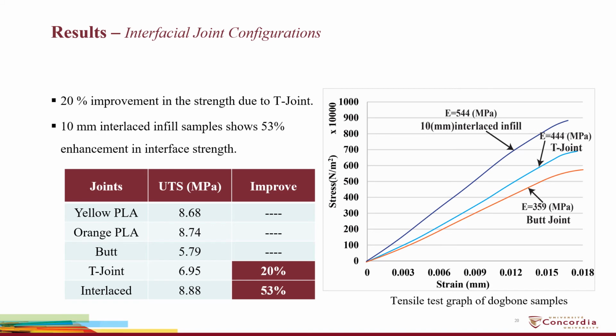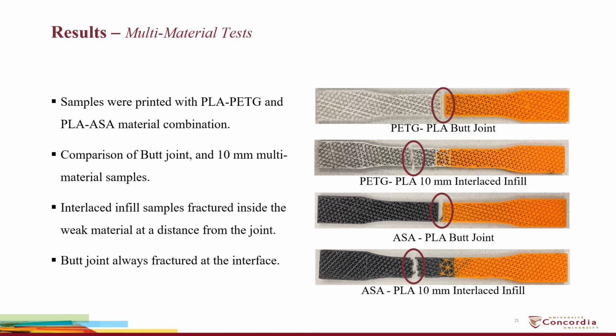For T-joint samples, we observed 20% improvement, and for 10 mm samples, we observed 53% enhancement in interfacial strength. This clearly shows that interlaced infill improves mechanical properties by 2x as compared to T-joint sample. To further analyze the efficiency of interlaced infill, we also compared multi-material samples printed with PLA, PETG, and PLA ASA material combination, and we observed the same trend, as none of the interlaced infill samples fractured at the interfacial joint.